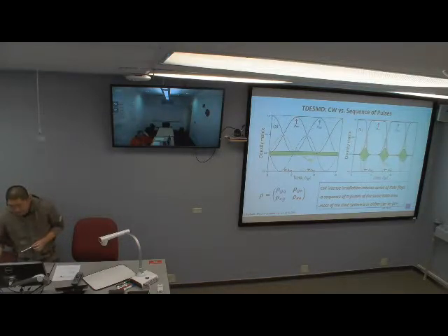And for the off-diagonal element of the density matrix, it is not 0 during the pulse activity, but it is 0 during the population period. So this means if we have a very short pulse, then our TDESMD calculation would be accurate because we do not need to worry about the off-diagonal element of the density matrix. And in most of the time, the system is either in ground state or in the excited state.